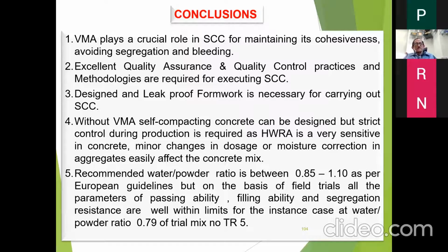The recommended water powder ratio is between 0.85 and 1.1, but on the basis of field trials and parameters of filling ability, passing ability and segregation, we could do the mix design with 0.79, as in trial mix 5, which means that more powder can be used. Because of more powder, there was a good finish, and because of more powder, the RCPT value would also go down.